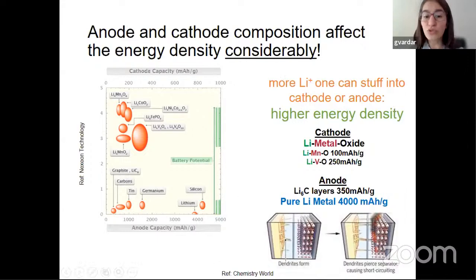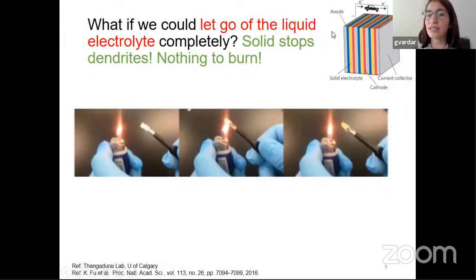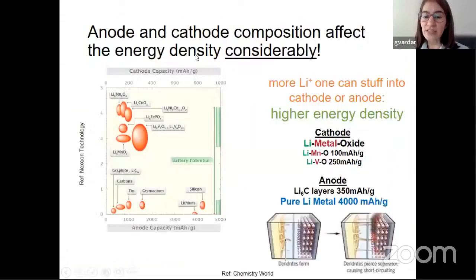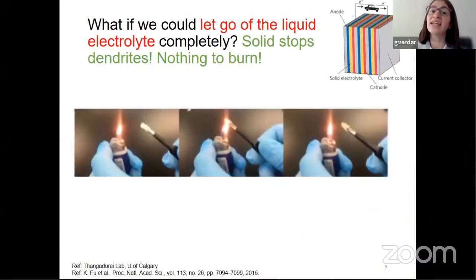So the solution to all of these problems is by basically letting go of the liquid electrolyte. Instead of using liquid electrolytes, we can have a solid electrolyte. This intermediary that shuttles the lithium back and forth, instead of being a liquid, can be a solid. Not only does the solid stop the dendrites, acting like a mechanical barrier that keeps the lithium dendrites from touching the other electrode, it is also non-flammable. Here you're seeing an electrolyte that goes into a flame, and